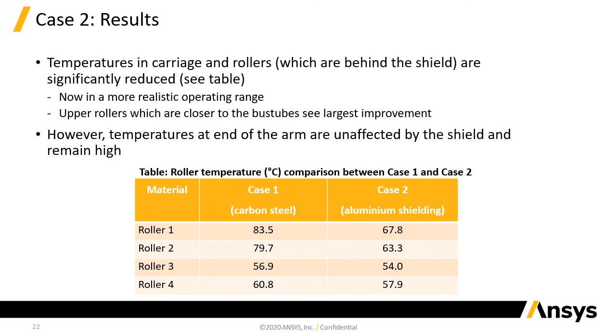So now if we have a temperature comparison, if we look at the table here at the bottom and compare the temperatures from case 1 to case 2, we can see that especially for the top rollers, there's quite a significant drop in the temperature in the rollers. Even the bottom rollers still see some reduction, maybe not as much, but they do see a drop in temperatures, which is quite a good thing.